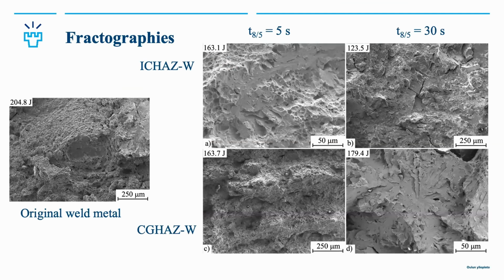Then some examples of fractographies by SEM. So in the original, it is mostly ductile, but even if in macro scale it is ductile, there are still some brittle areas that can be spotted. And here is a good example: we have ductile fracture here and also here, but between them there is a region of brittle fracture. And this is quite well connected to the microstructure, that we had mainly acicular ferrite, but then we had these grain boundary ferrites. And these grain boundary ferrite areas seem to have brittle fracture, while in acicular ferrite regions, it is ductile fracture.